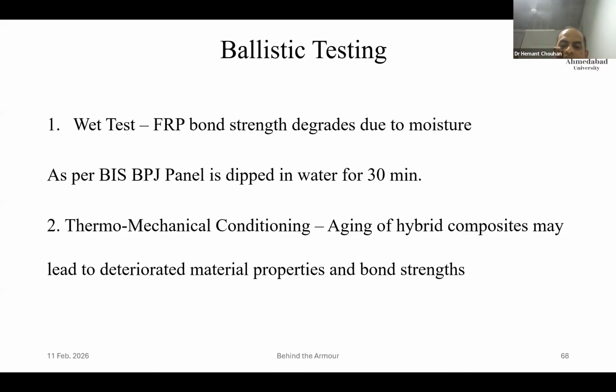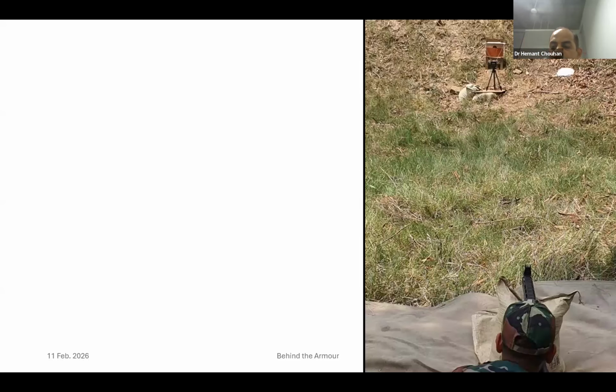Then in thermomechanical conditioning, there is an 11-day cycle, at the end of which, on the 11th day, your panel is equal to a 1 year aged, 5-year aged panel. So that is basically the aging cycle for a hybrid panel, so that after 5 years also it should stop the bullet. And this is how we test it.